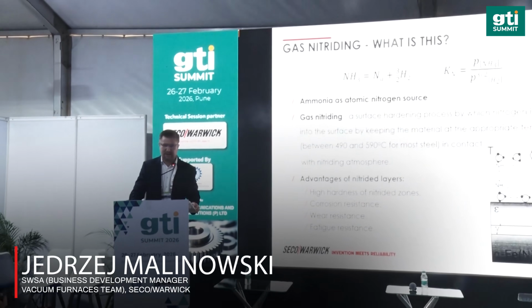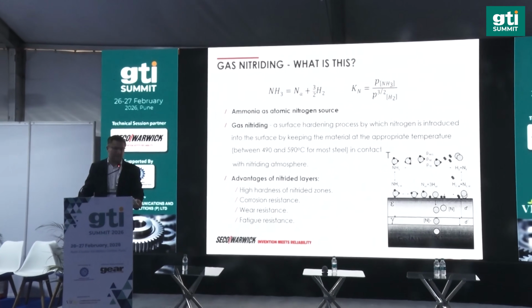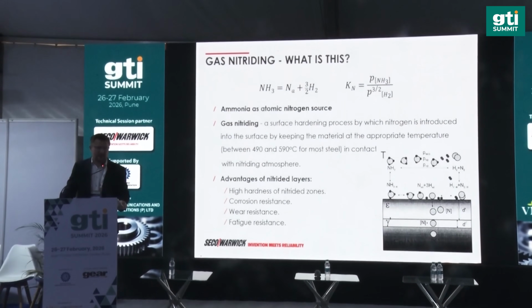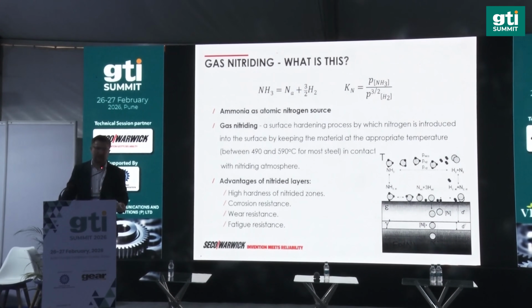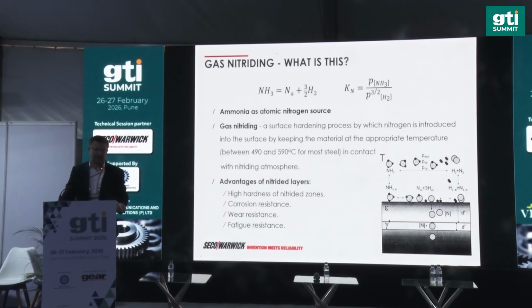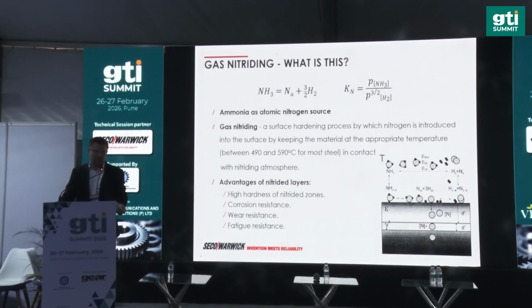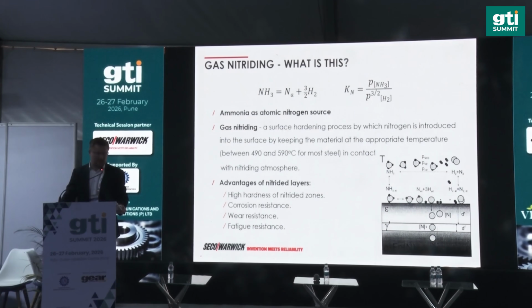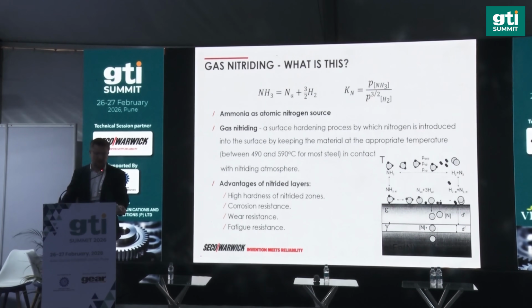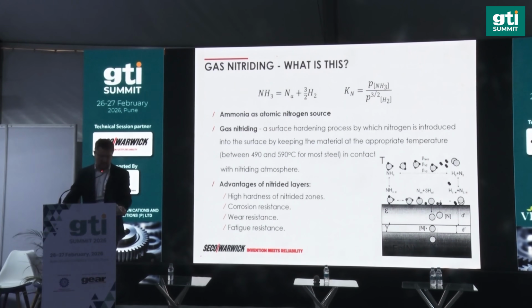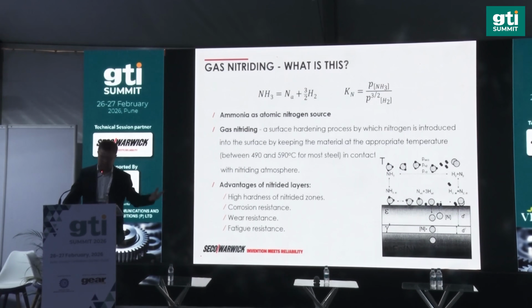Generally, you probably know nitriding very well, but just to remind, it is a thermochemical process based on the diffusion of nitrogen. We can easily compare it to gas nitriding, but in this process we are talking about the diffusion of nitrogen to the surface of the steel, and as the gas which supplies the nitrogen, we are using ammonia. Ammonia is dissociating inside of the furnace, and the atomic nitrogen is diffused to the steel surface, and the hydrogen is burned outside of the furnace.